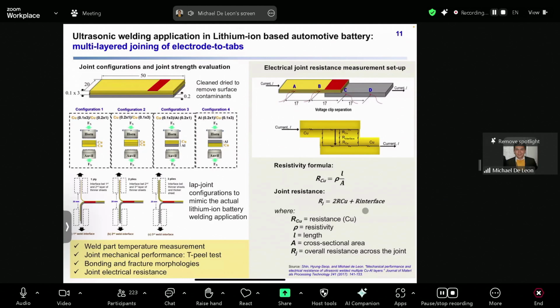So what is our goal here? Here is the overview of the systematic approach we undertook to characterize the weld quality. Our approach here is comprehensive. We first measure the temperature distributions during welding using an infrared thermal imager. Then we analyze the joint strength mechanically, and also the fracture morphologies. Lastly, we verify the electrical performance. It's this combination that gives us true insight into weld quality.